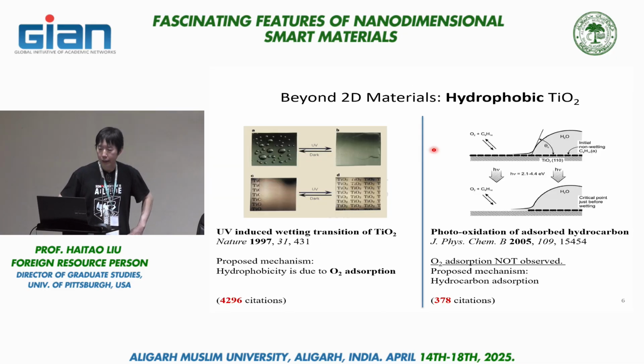So I didn't get a chance to discuss this, but yesterday I talked about all this contamination on 2D material, and even beyond 2D material, this behavior happens on pretty much everything. Okay, and I'm going to show two examples. One is TiO2. There's this very well-known wetting transition reported back in 1997, where they showed that the TiO2 surface can switch between a hydrophilic and a hydrophobic state. Exposure of the TiO2 to UV light makes it hydrophilic, and if you leave it in the dark, it becomes hydrophobic. This is a very interesting behavior, certainly.